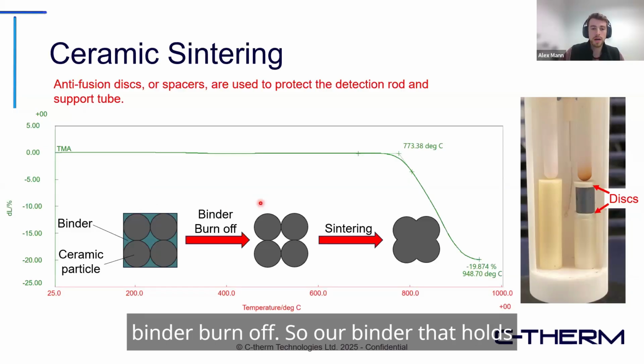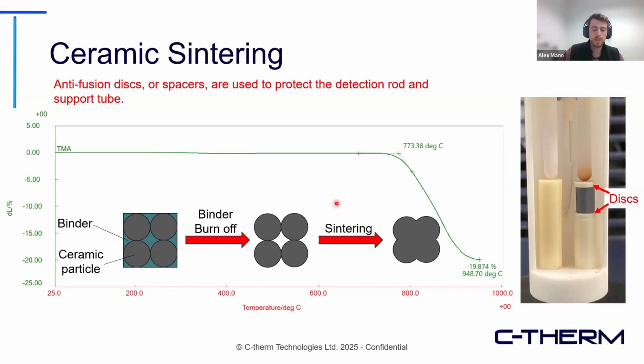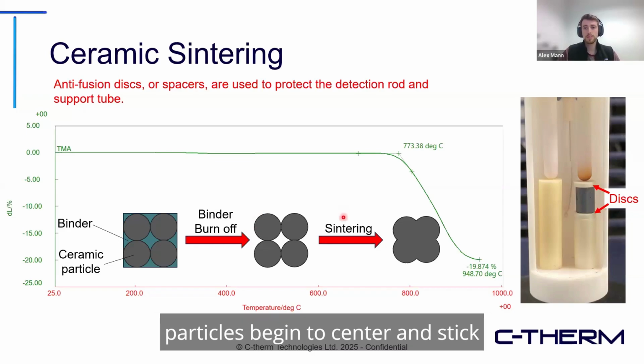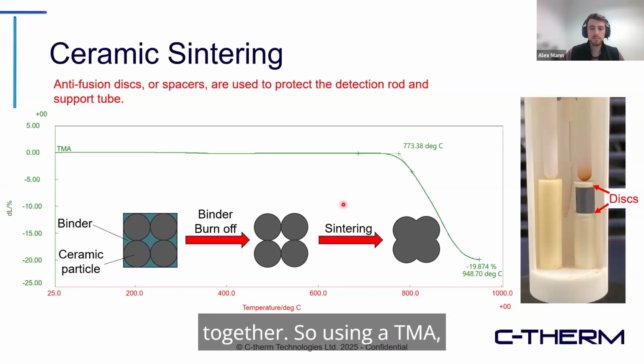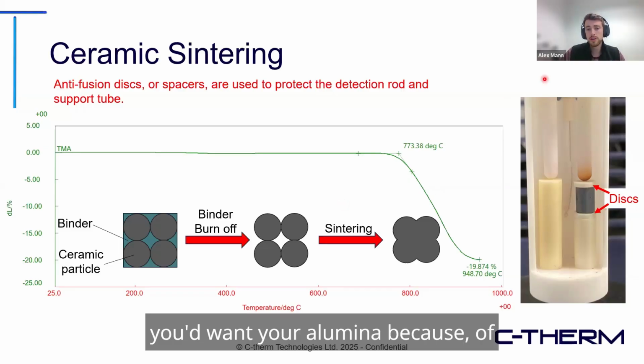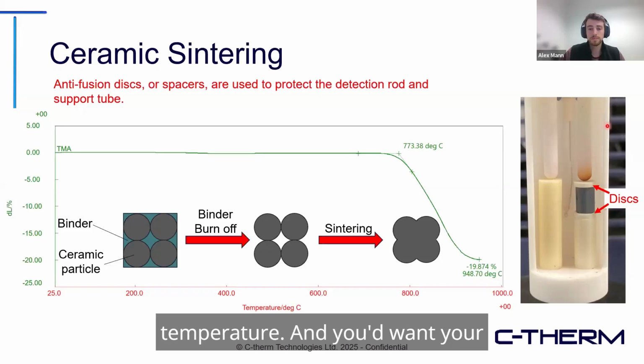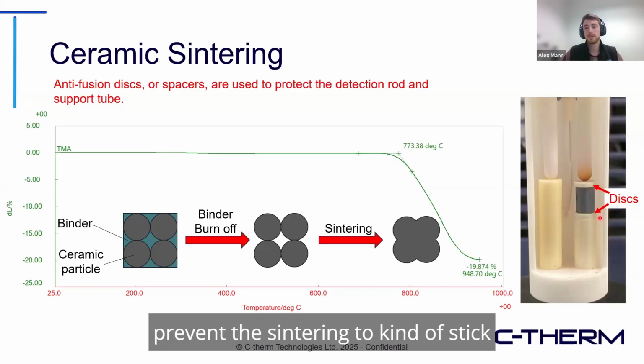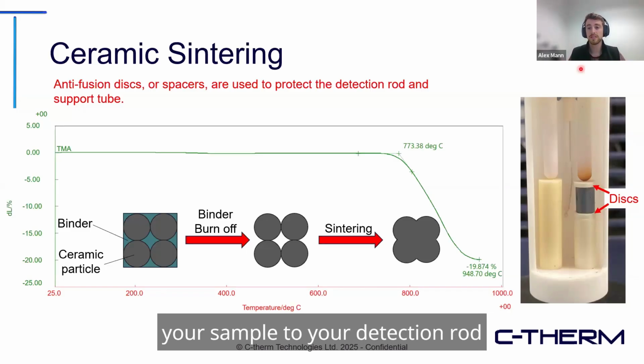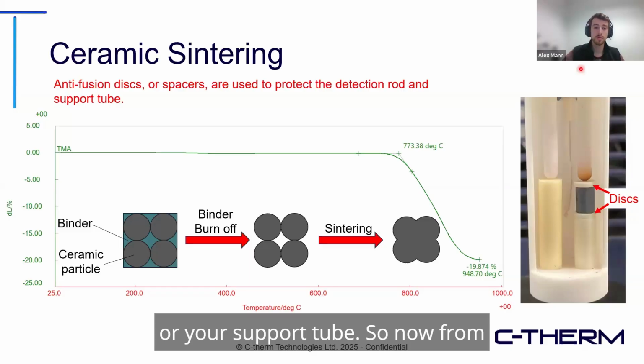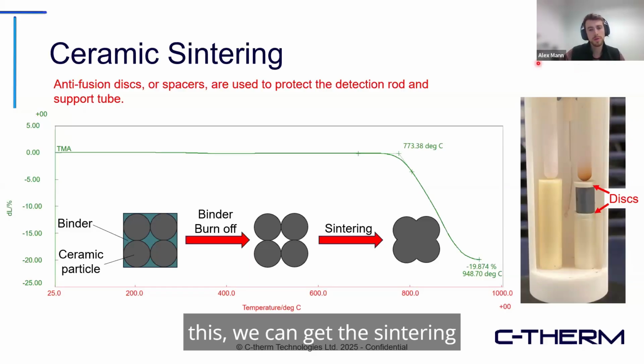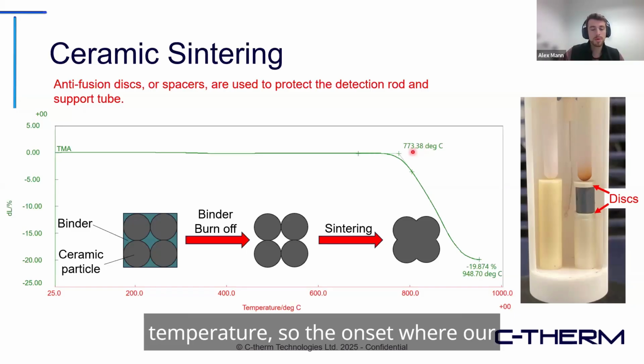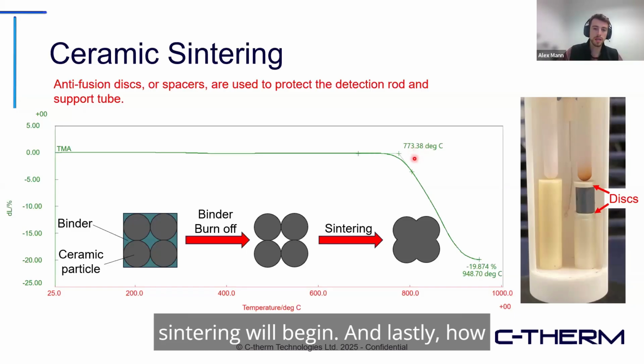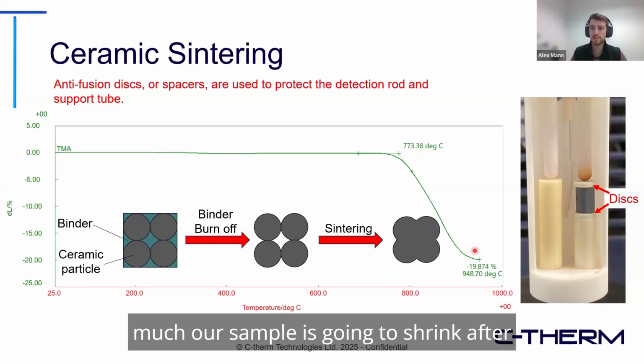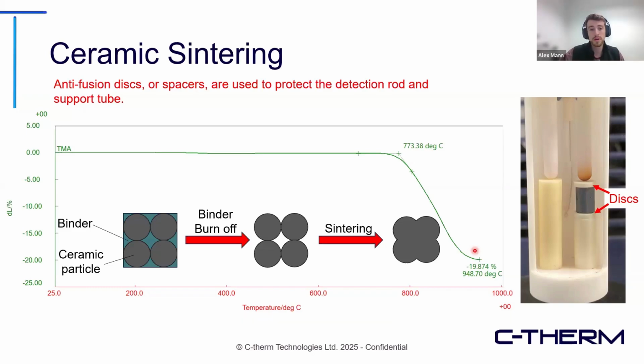So our binder that holds it together goes away. And then as we reach really high temperatures, the particles begin to sinter and stick together. So using a TMA, you'd want your alumina, because of course we're reaching a high temperature, and you'd want your anti-fusion discs to prevent the sintering from sticking your sample to your detection rod or your support tube. So now from this, we can get the sintering temperature, so the onset where our sintering will begin. And lastly, how much our sample is going to shrink after it's fully done.